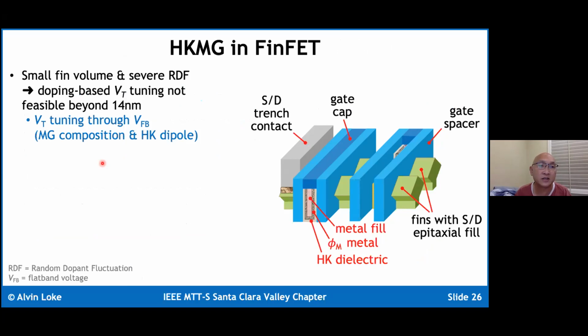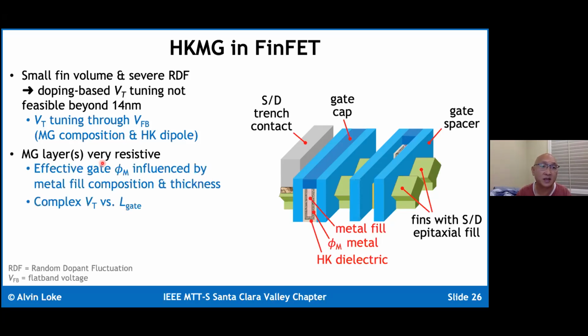The key thing here is as we keep scaling the gate length shorter and shorter, there's less fin volume that the gate wraps around, which means that if you were to use implants to give you the different VT flavors, it's becoming less and less effective. You're getting back the random dopant fluctuation you fight hard to eliminate in fully depleted devices. And so in the most advanced nodes, the VT tuning is done exclusively through flat band voltage adjustments, which is basically through changing the metal gate composition or the use of HighK dipoles, okay?